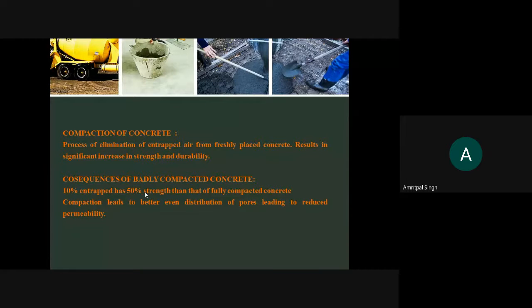If the concrete is not well compacted, it leads to a porous concrete and segregated concrete, and a lot of air is entrapped in it. And it has been established by research that a mere 10% entrapped air results in a 50% reduction in the strength of concrete as compared to that of a fully compacted concrete. Compaction, in addition to increasing the strength, also leads to better even distribution of pores, which will lead to reduced permeability.